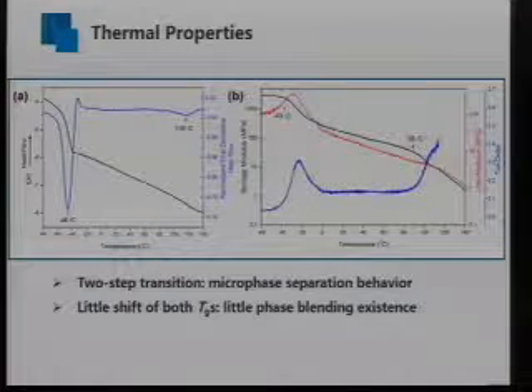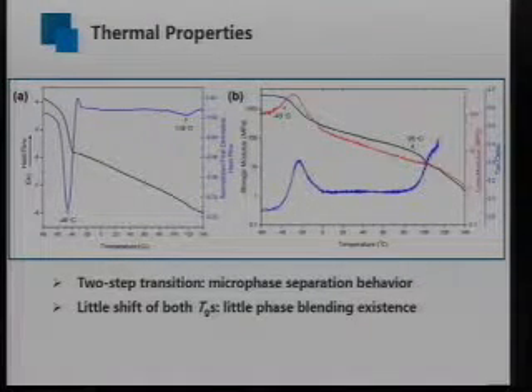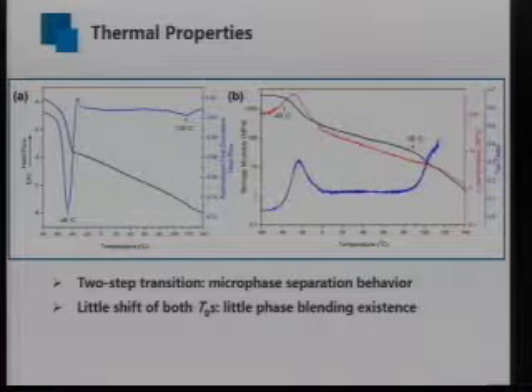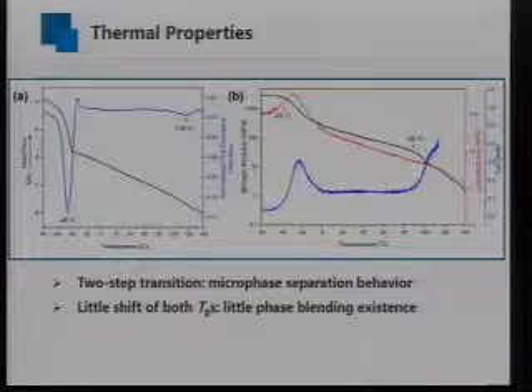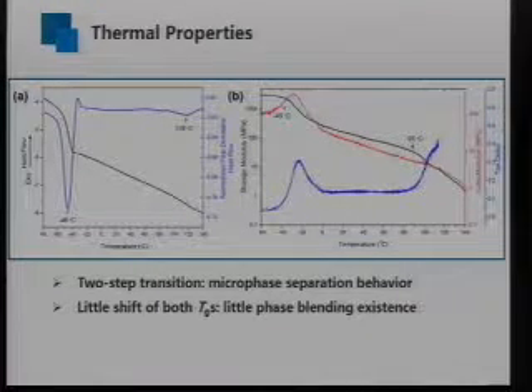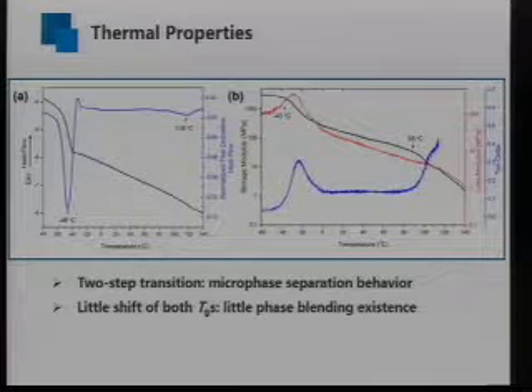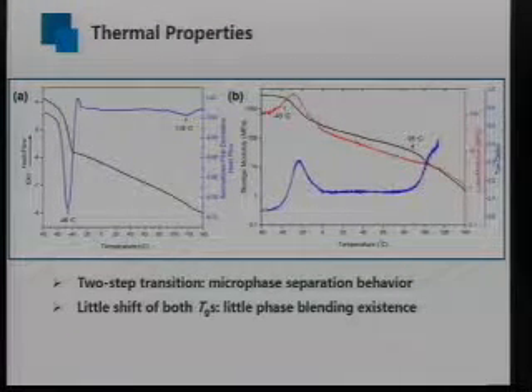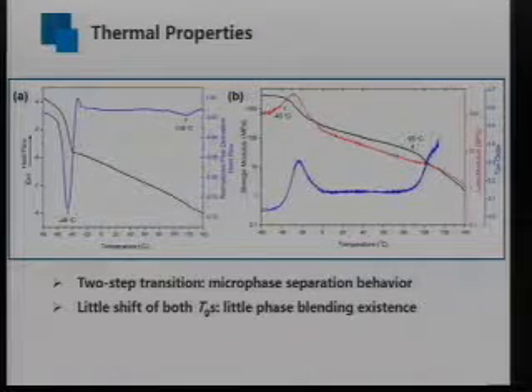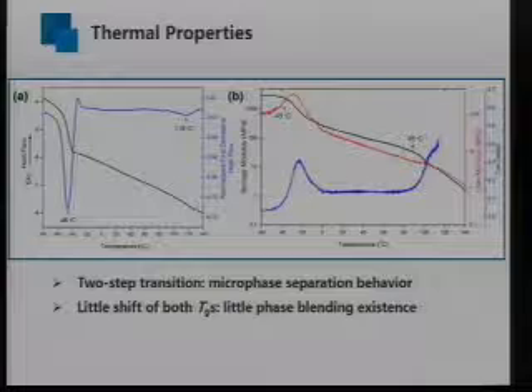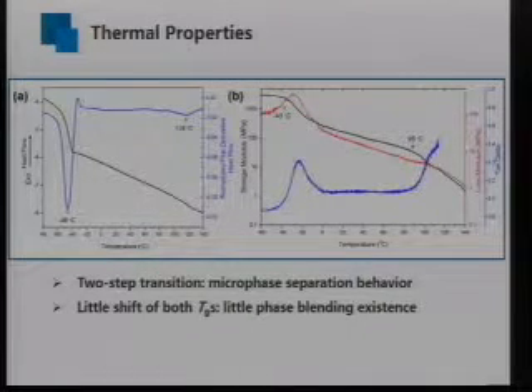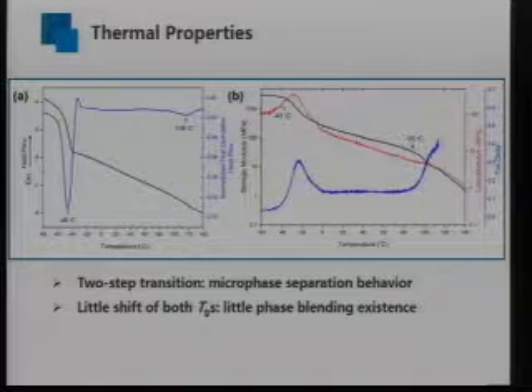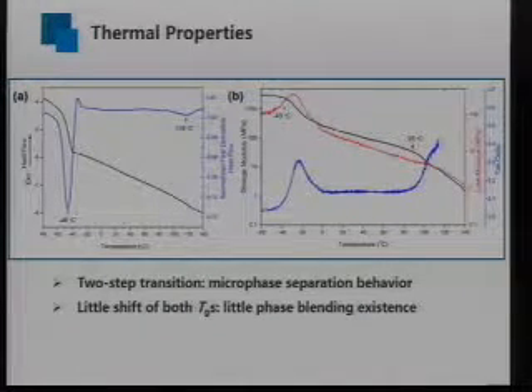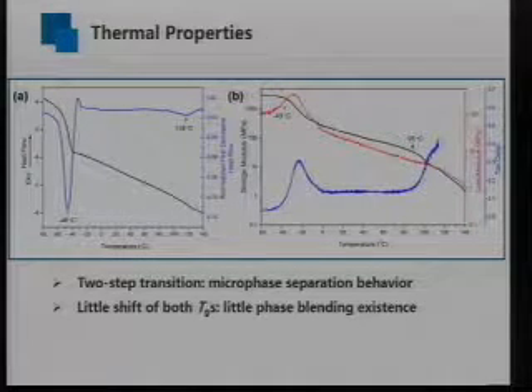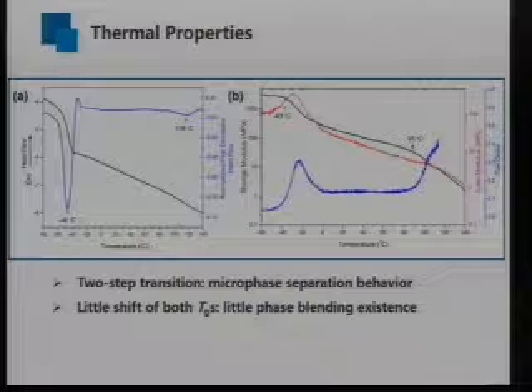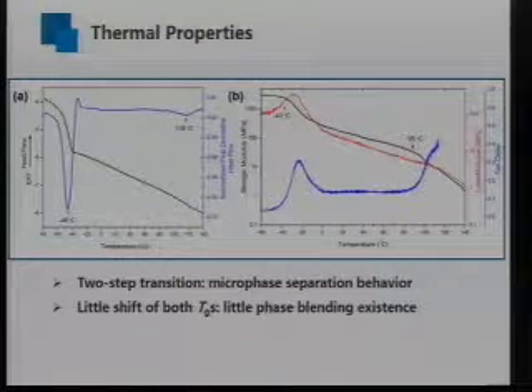From both differential scanning calorimetry and dynamic mechanical analysis, we can see a 2-step shift with the change of the temperature. This 2-step transition is the indication of the microphase separation behavior. Also, comparing these glass transition temperatures with those of the homopolymers, they are very similar. So this little shift of both glass transition temperatures means little phase blending exists in the final block copolymer, which means the microphase separation behavior of this final block copolymer is very strong.